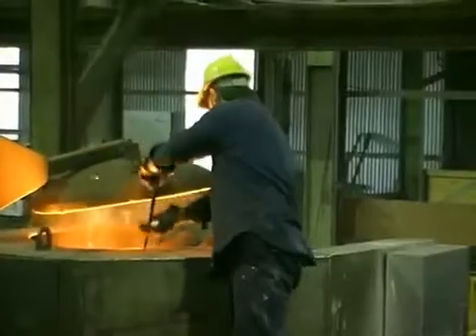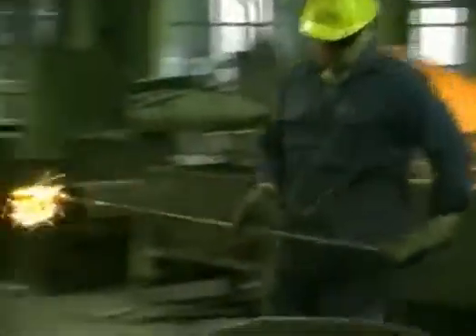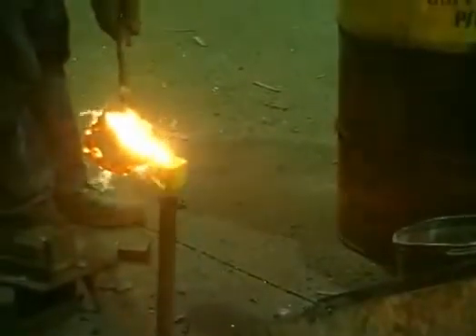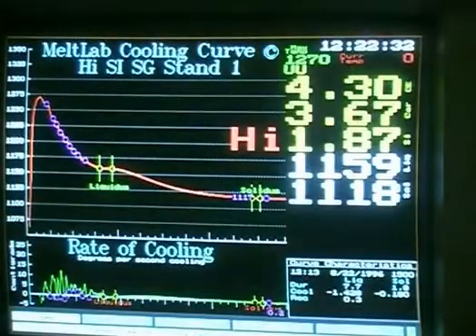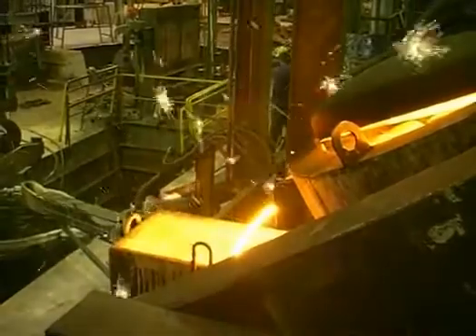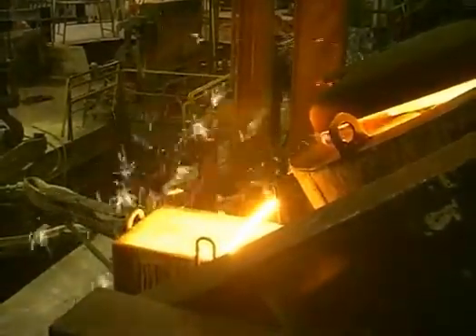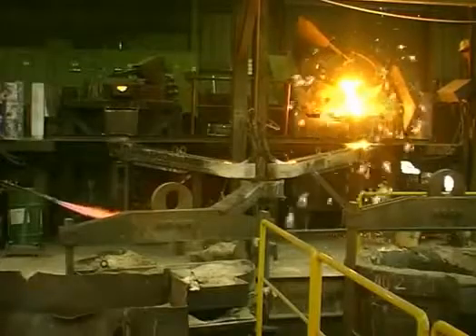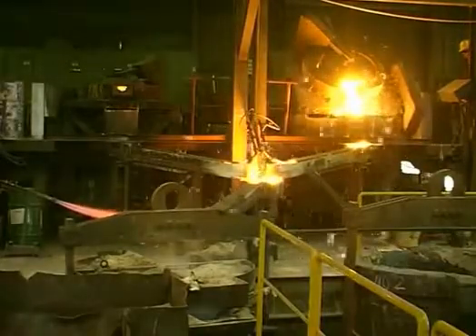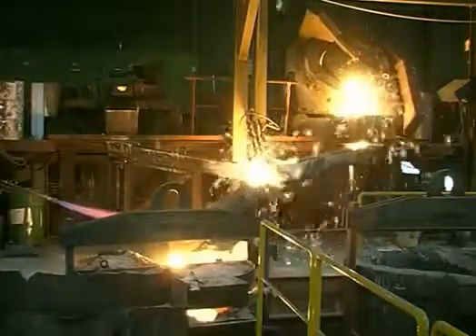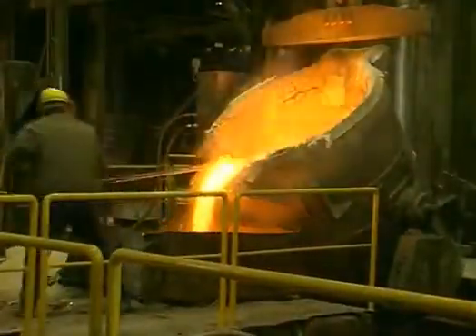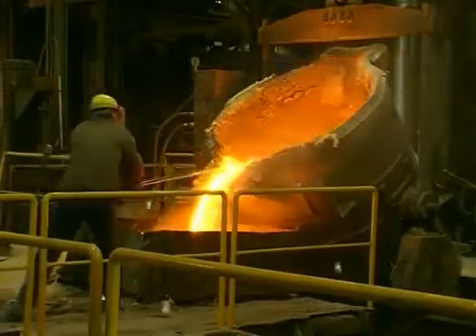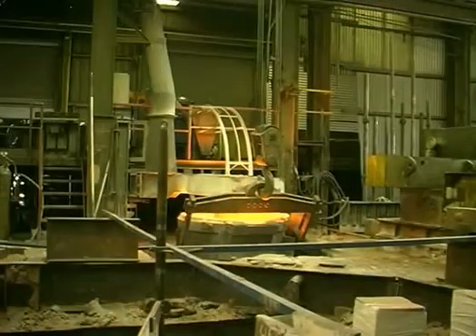Cast iron and steel scrap are loaded into the induction furnace. A sample of the melt is taken for computer-aided chemical analysis. You have to get your metallurgy right if you are to produce quality castings. When composition and temperature are correct, the ladle is filled. Slag is raked off. Magnesium and inoculants are added.